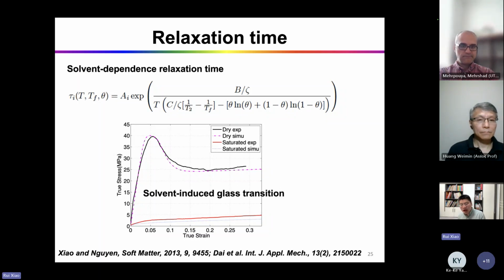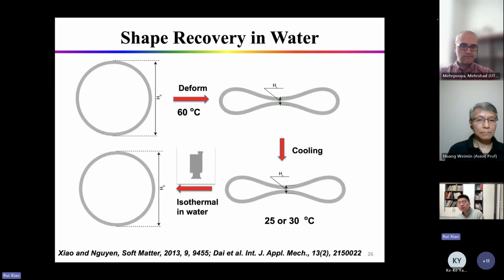But this is not enough for modeling shape memory effect. You also need to simulate the diffusion process. So this is a test of what we do. We have a tube, and we program it to this shape, and we put that in water, and use a camera to record its recovery.